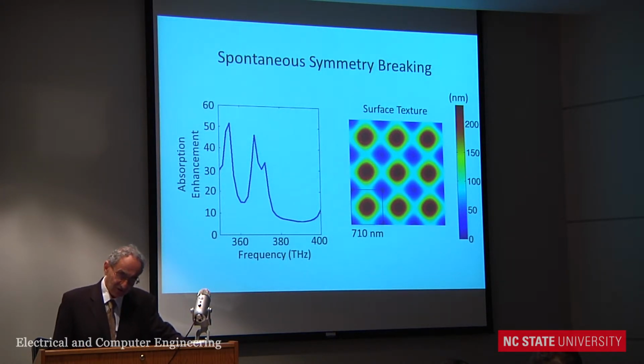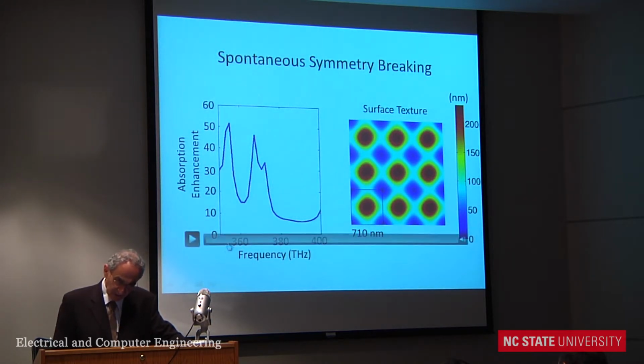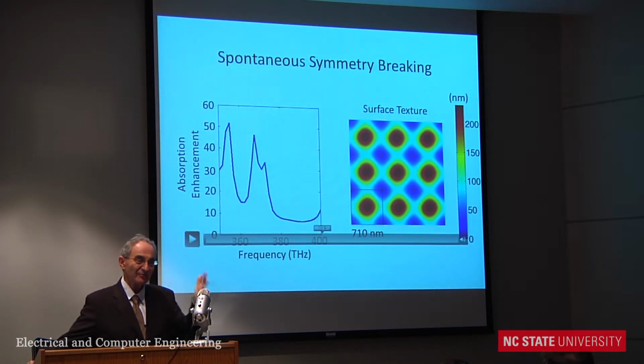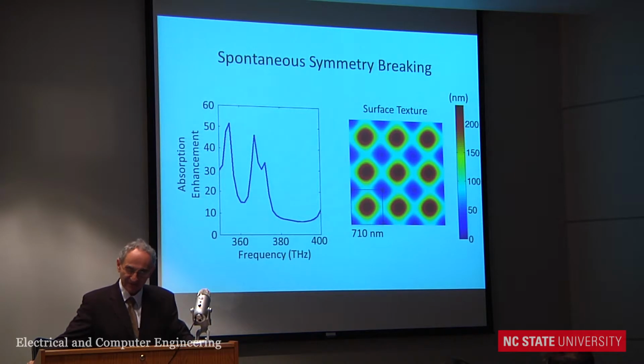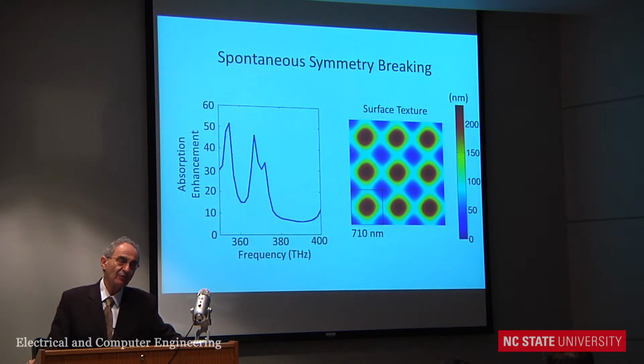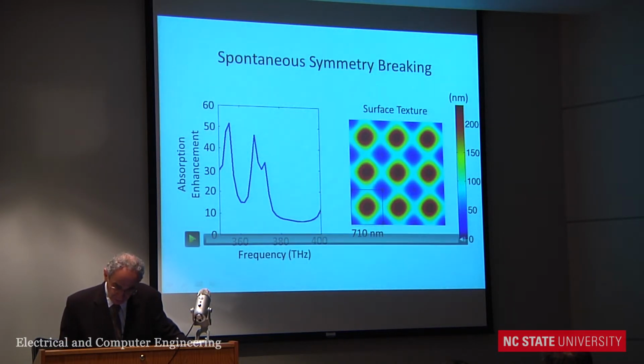Now, gallium arsenide, although it has a direct band gap, near the band edge it's not such a strong absorber. And so she was covering this region between 350 and 400 terahertz. By the way, I don't like wavelength, I prefer frequency, so this is in the near infrared. And the gallium arsenide is not that absorbing, and I need to optimize it. And she was looking for this 4n squared factor and see if she could get close to it. And so she did this optimization. It's an iterative optimization. Let me show you the movie.